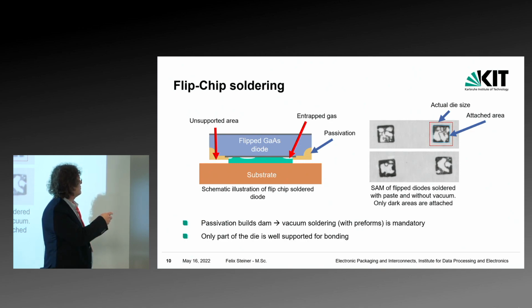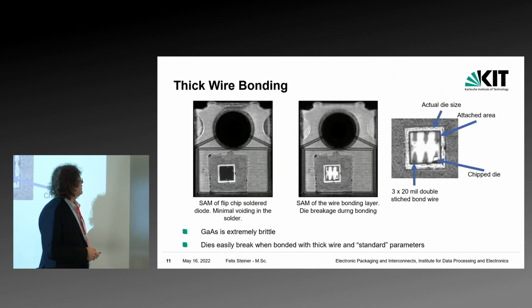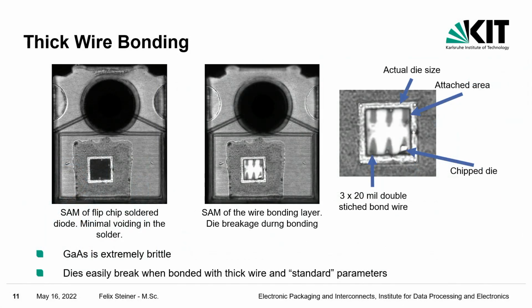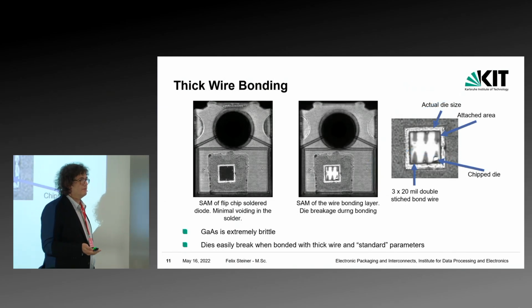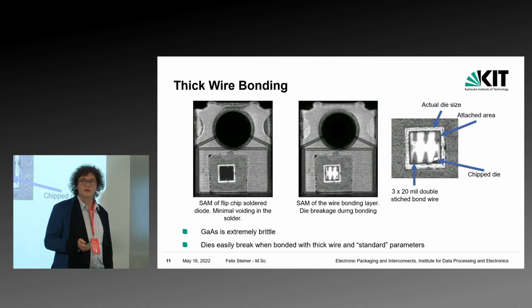But the other problem is the unsupported area where there's no solder on the edges where the passivation is. If you go with vacuum soldering, you get a really nice attachment, as we see on the left. And in the image in the middle, we can already see a little problem with gallium arsenide. The image on the right shows it in more detail. This is a gallium arsenide diode bonded with 500 micrometer wire with just normal standard factory parameters. And there you see a chipped piece of gallium arsenide where the bond was. So gallium arsenide is extremely brittle, and you have to account for that with bonding.